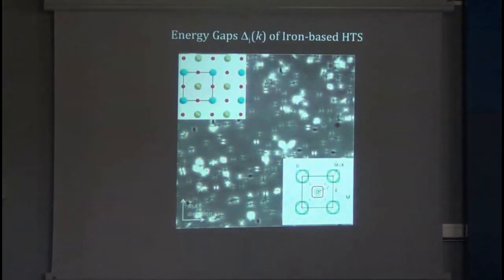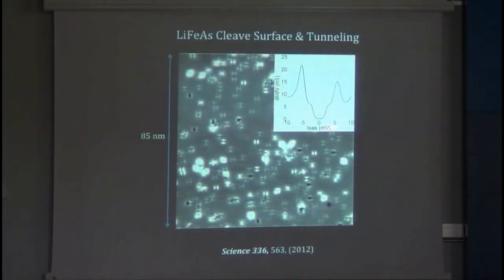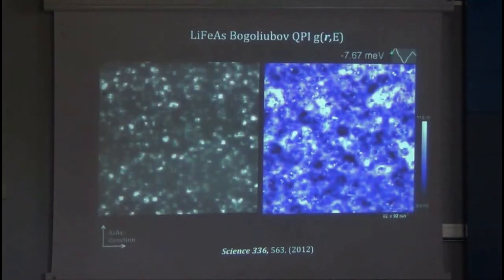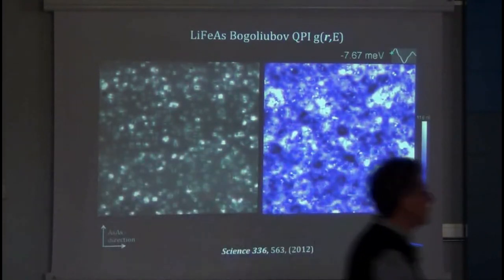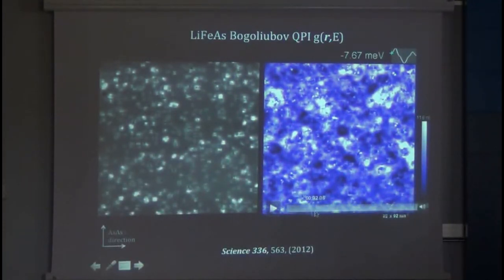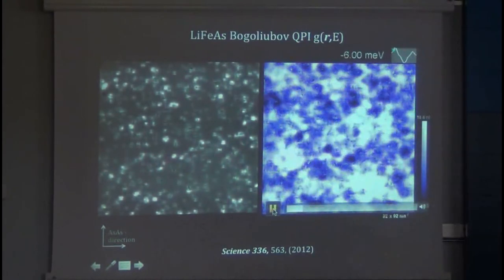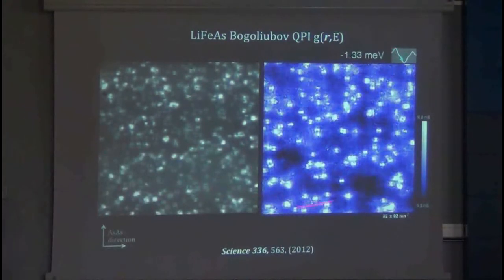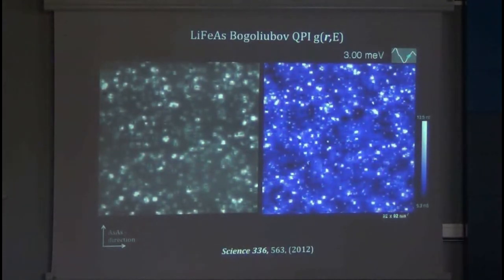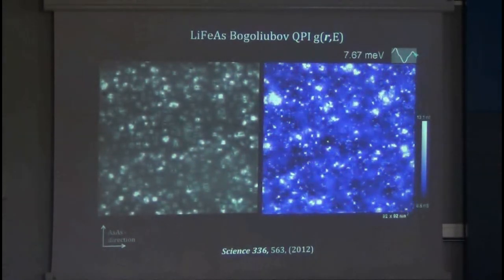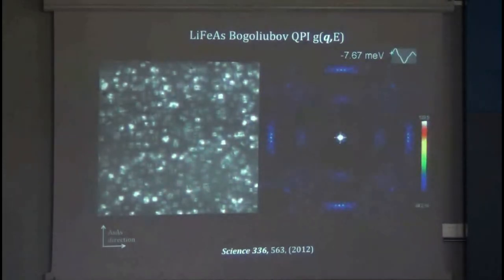The other thing we can do is look at the superconducting energy gaps of this same class of compounds, and for this we used lithium iron arsenide, which it turns out to be a very useful material, has a very nice superconducting density of states, a very nice clean, flat, stable surface. On this surface, we were able to image the superconducting quasiparticles with atomic resolution. There's the image. This is the first movie ever made that we know of Bogoliubov quasiparticles in an iron superconductor, and it looks like a mess. However, its Fourier transform looks quite beautiful.